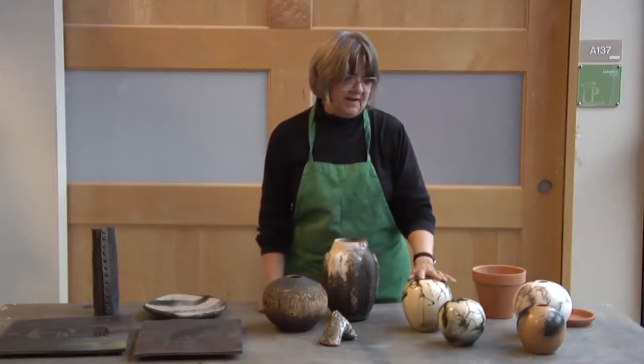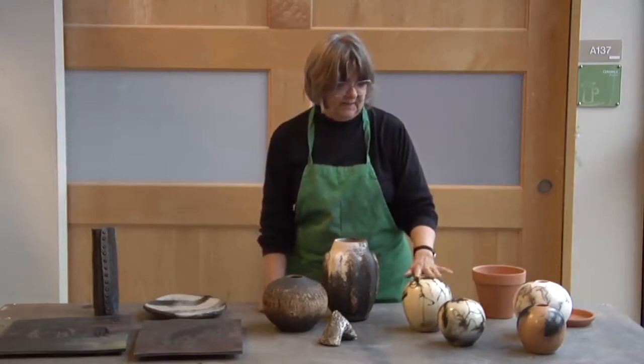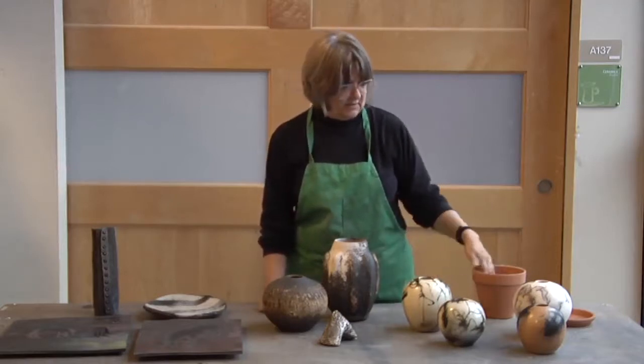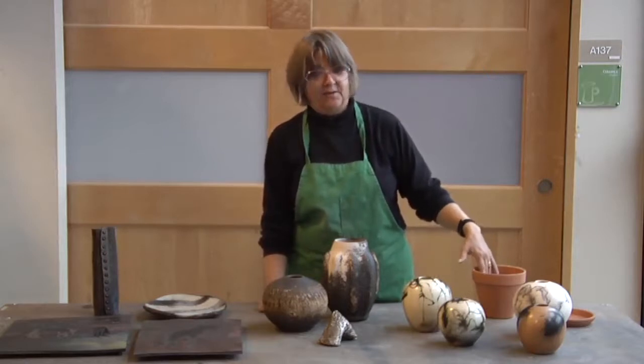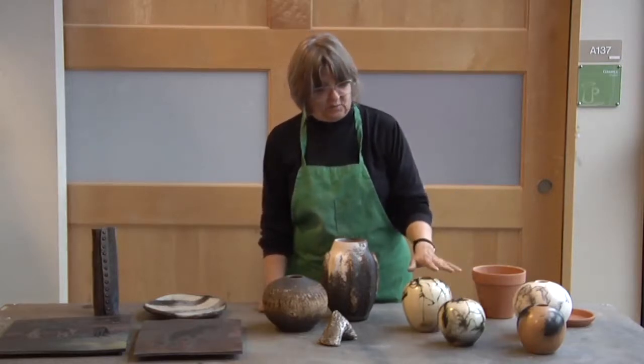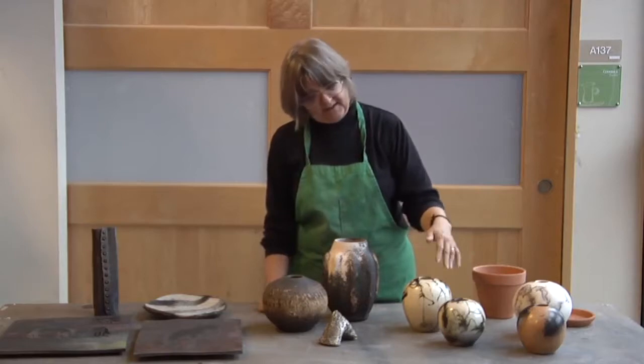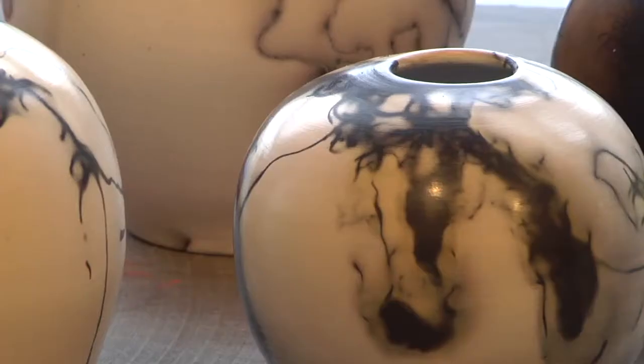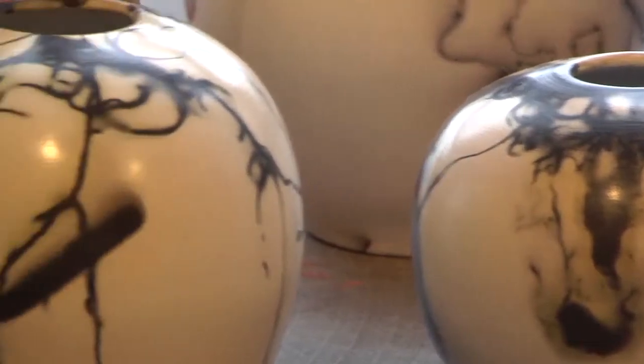So then this is fired to 1650, held for about 10 to 20 minutes so that everything combusts in the saggar, and then it's let to cool. Come back and take it out when it's touchable. You don't want to take it out too fast.